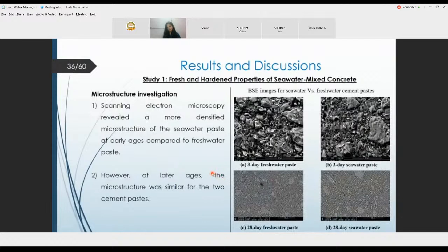The microstructural investigation conducted on study number 1 using scanning electron microscopy revealed a more densified microstructure of the seawater paste at early ages compared to freshwater paste. However, at later ages, the microstructure was similar for both pastes.